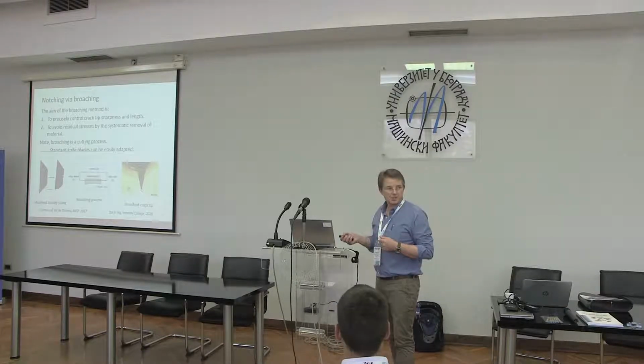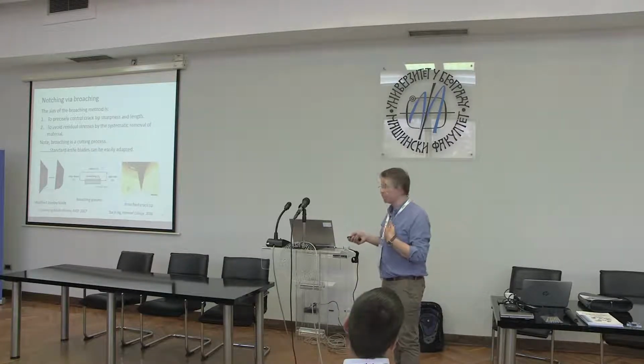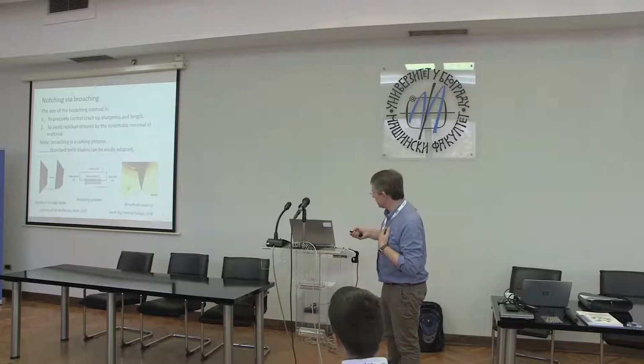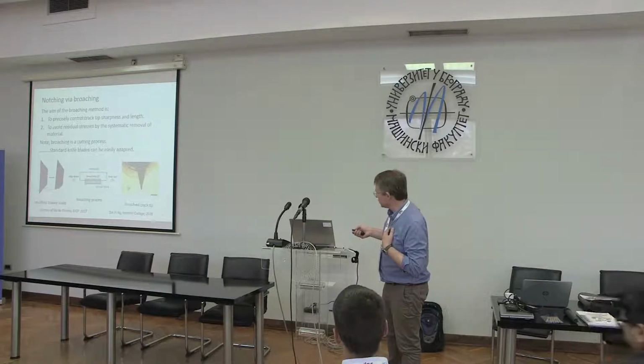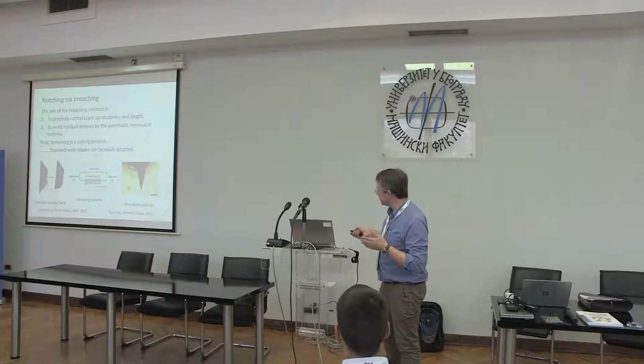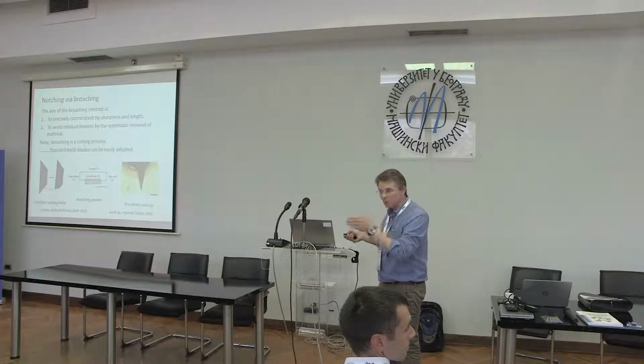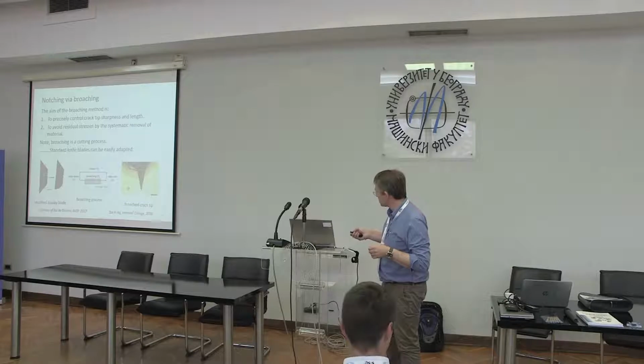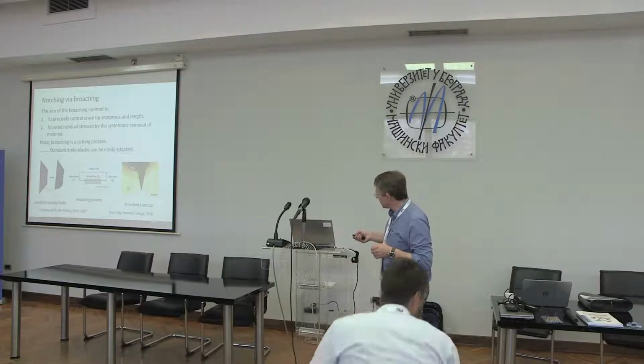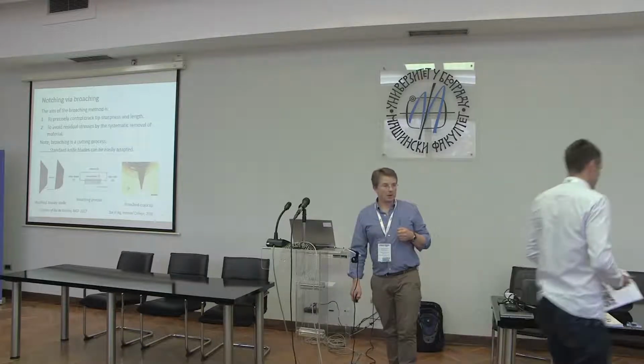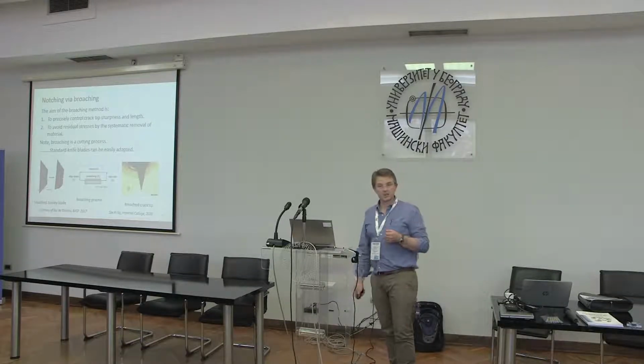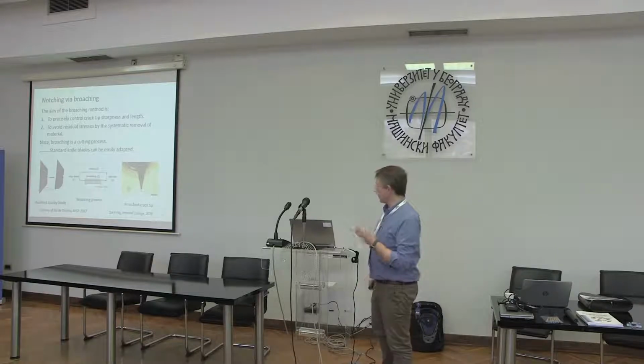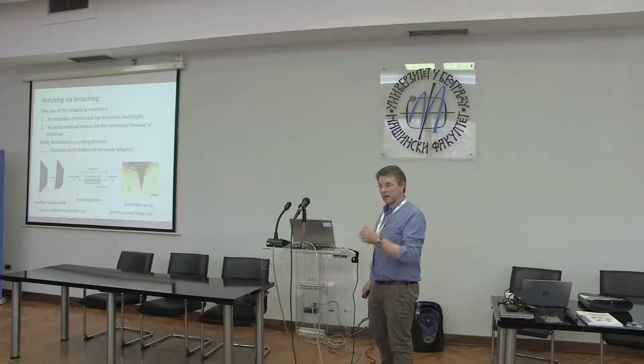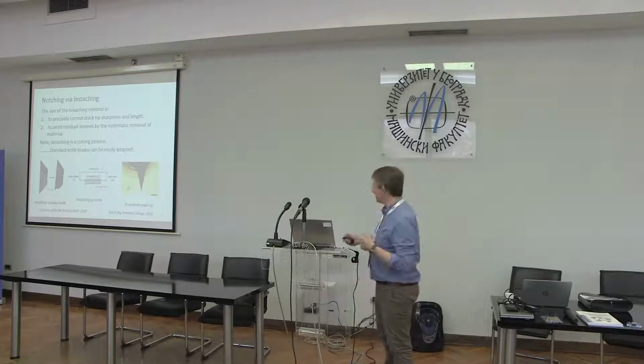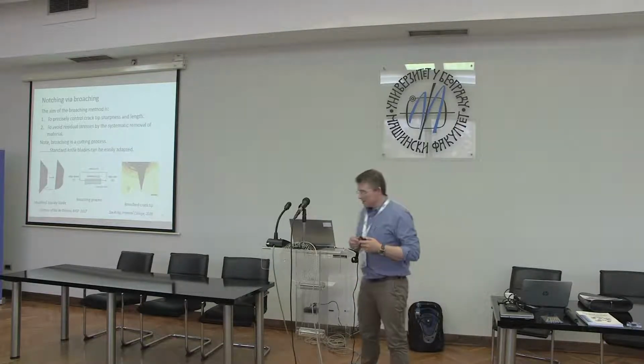So this was some notching, this was some broaching performed by a student in our lab, and you can see this was the milled notch, and then this is the broached notch. And you can see the broached notch has been made by incrementally taking this blade and working it into the material. So you can almost see the steps in this process. And she's got down, in this case, to a notch tip radius of about 2 microns. And the nice thing about that radius is that we can measure it, we know exactly what it is, we can control the depth of that, and we can control the direction of it. And we think there are no residual stresses underneath.